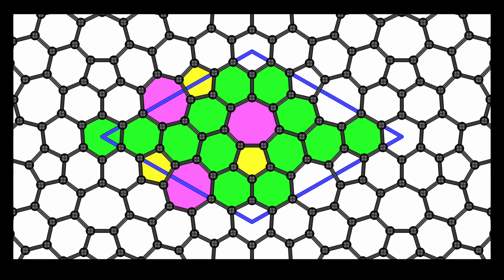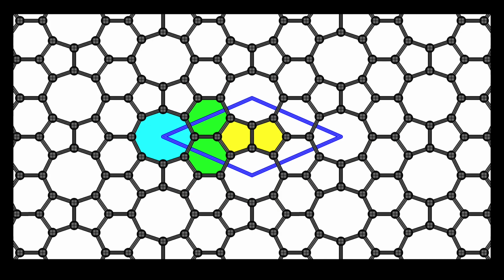This one is a little bit more, but the advantage is the green shapes, which are hexagons, do not count, right? So we see that we have 3 pentagons and 3 heptagons, so the average is indeed 6. And you keep going and so on and so forth. So you see here, again, last one I'm going to describe in detail, 2 pentagons and 1 octagon, the average size is 6. And we can keep going.